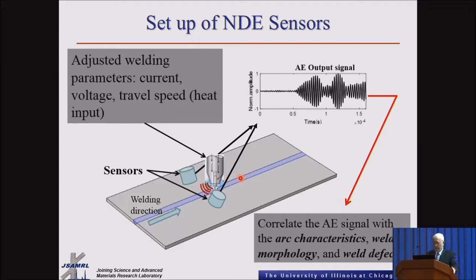So based on this brief introduction, what we wanted to do is take our welding torch and then try to introduce some sensors close to the torch, which involve not only acoustic emission but also non-contact ultrasonics, so that we can detect any changes during welding, not only of the welding arc, but also of some of the changes that might be going on as you are producing the weld. And what we're trying to do is, again, correlate some of the changes that you get in the signal that might be related to the arc, but also could be related to some of the defects that are being introduced during the production of the weld.